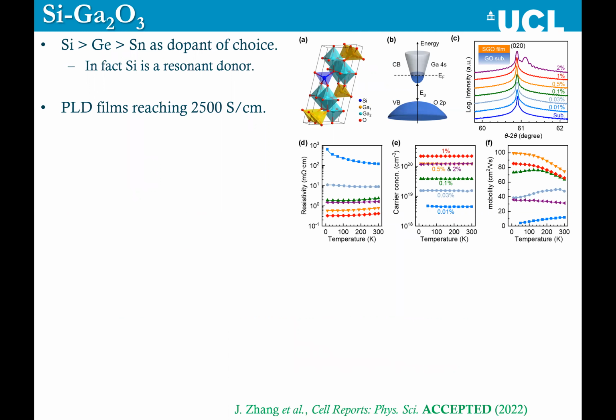And recently we showed in a paper that was actually just accepted this morning in Cell Reports Physical Science that silicon acts as a similar type of dopant in gallium oxide. So gallium oxide is an oxide that is probably the sexiest oxide in the world right now, because it has a 4.9 electron volt band gap, so a huge band gap. And it's used for, or they're trying to use it for power electronics, because the bigger a band gap in a power electronic system, the better the breakdown field, the more power you can put through it, and the thinner the device you can make. So this is a material that everyone is interested in at the moment.